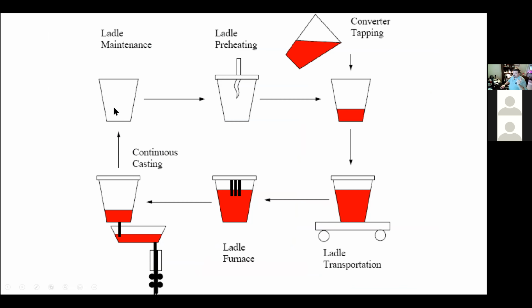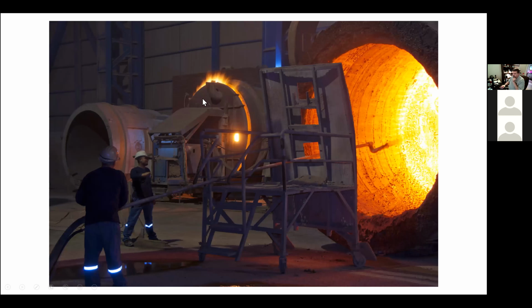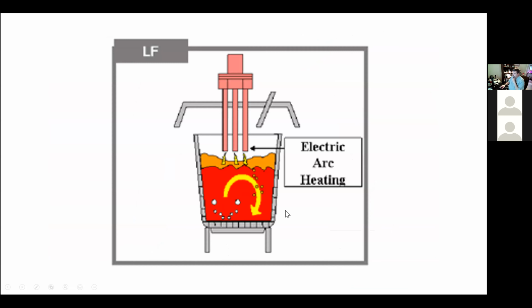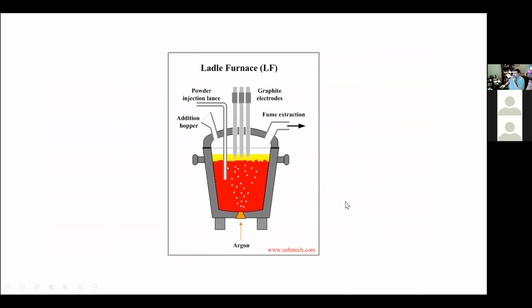So this just shows the typical cycle. You have this ladle, you tap into it, it gets transported to the ladle furnace, then to the caster. Afterwards, it gets cleaned, then it gets put on a stand where it gets heated. It's called a ladle preheater, which is what you saw right here. So this is basically a panel that's refractory lined on the inside and has a big burner that's used for heating the inside of the ladle. And this just gives you an example of the ladle furnace. Pretty straightforward.